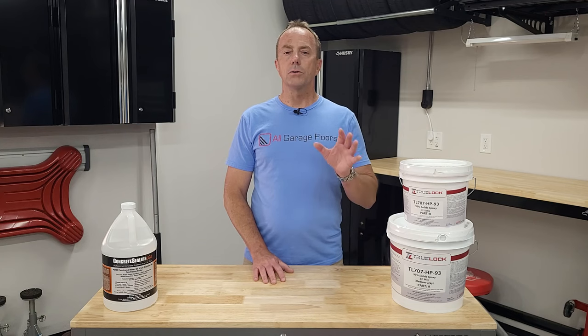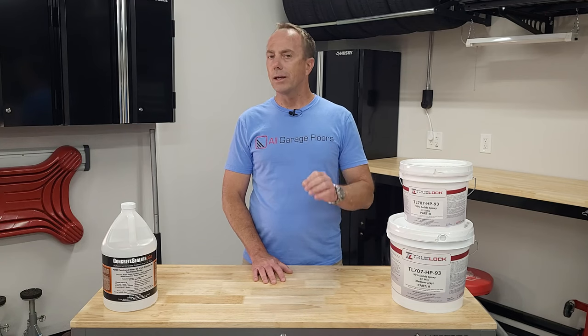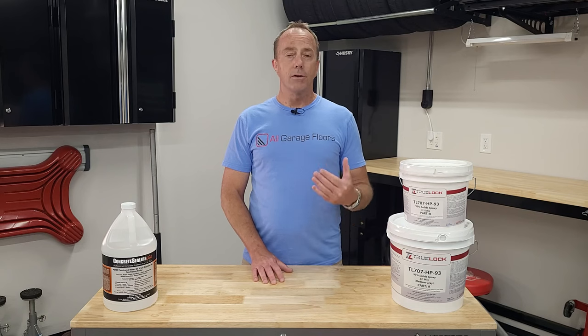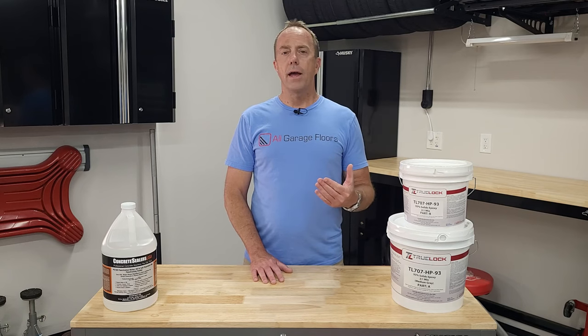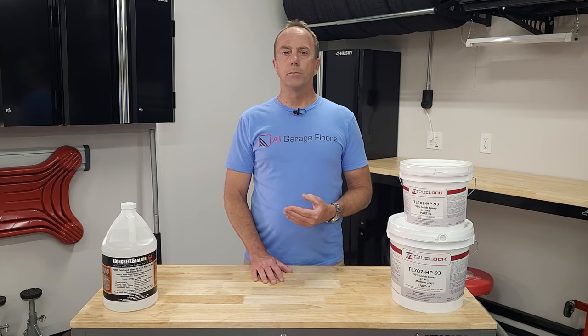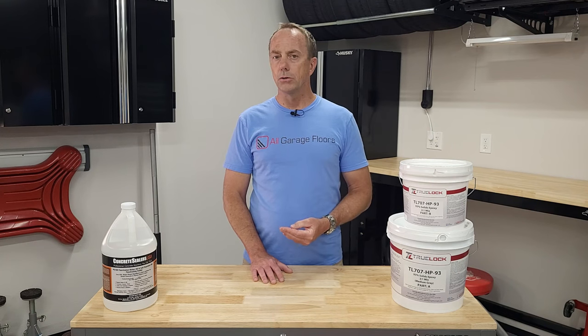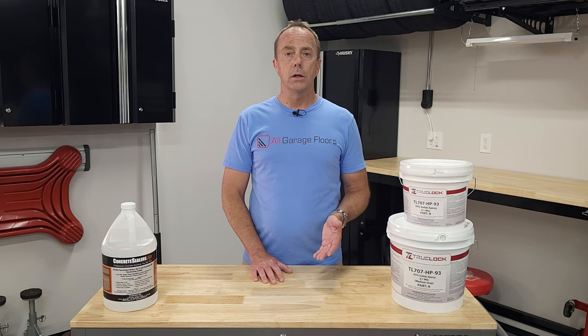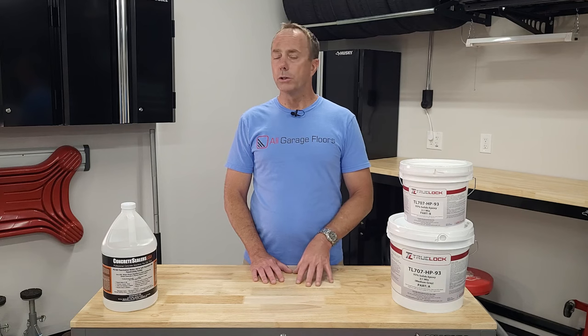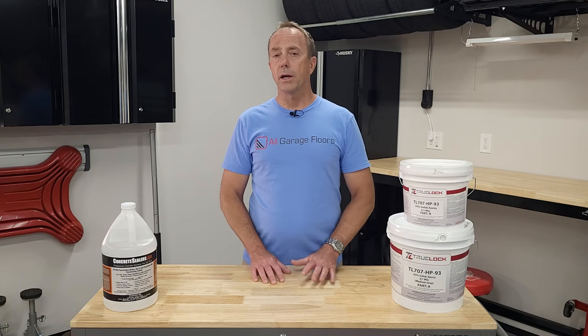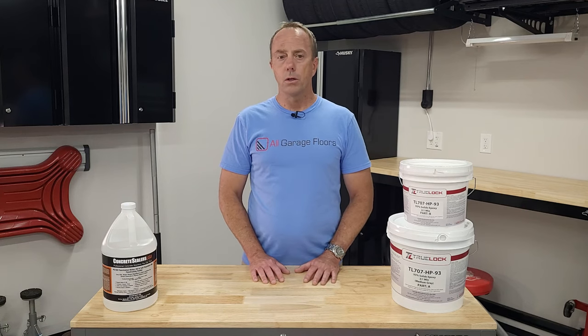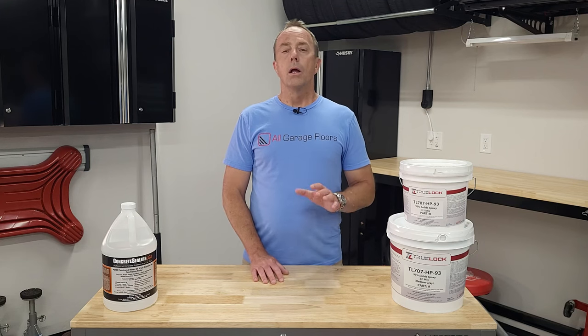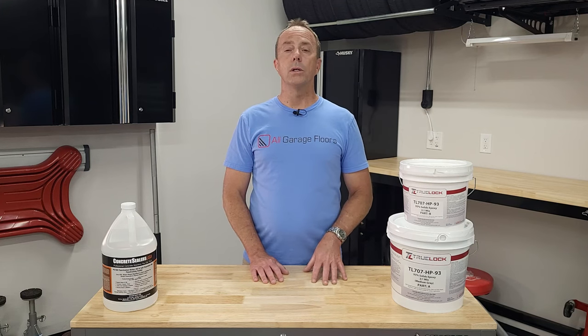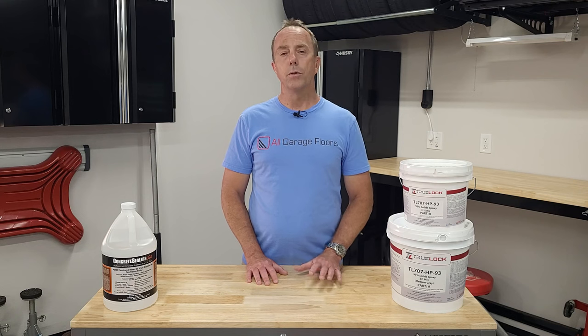Coatings are also susceptible to moisture in concrete. So if you have a garage floor that looks wet at times, or you know has some moisture issues, you may not want to do a coating. We highly recommend that you do a moisture test first before you decide to go with any type of coating on your garage. Something else to be aware of is that coatings get very slippery when they're wet.